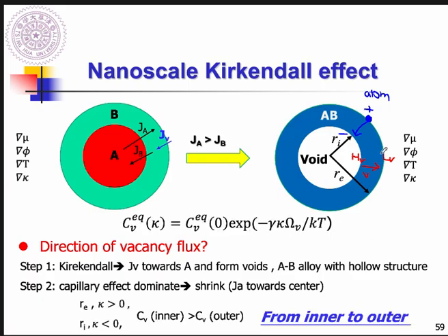So no matter whether it's based on the atom's point of view or the vacancy point of view, the morphology evolution of this hollow nano particle will be shrinkage, which means that the diameter of this nano particle will decrease as a function of time until the driving force disappears.